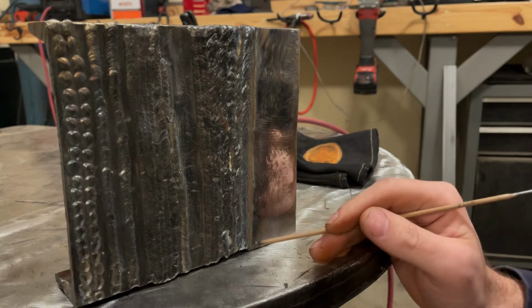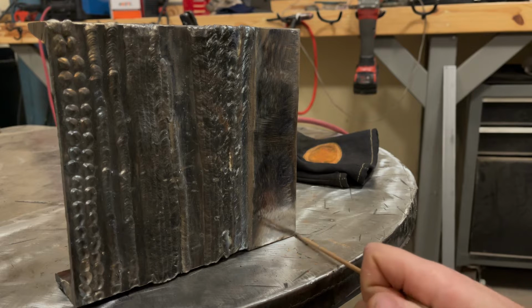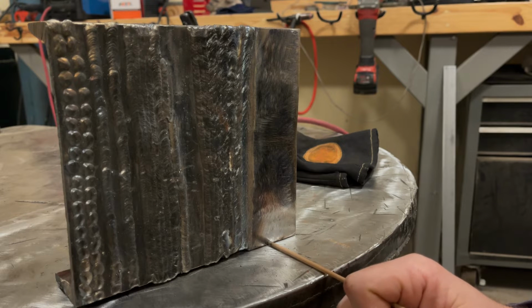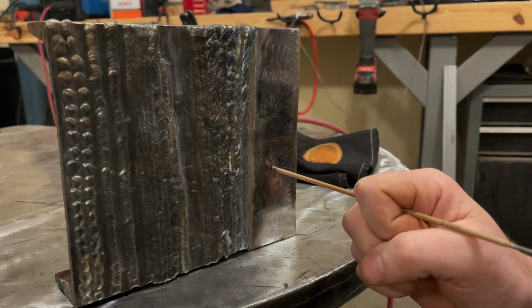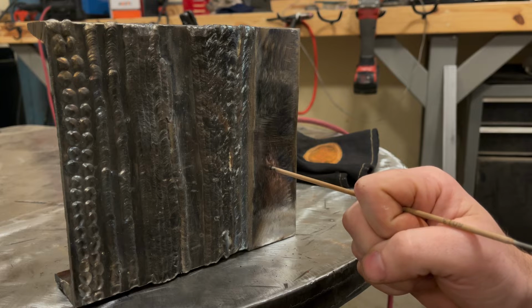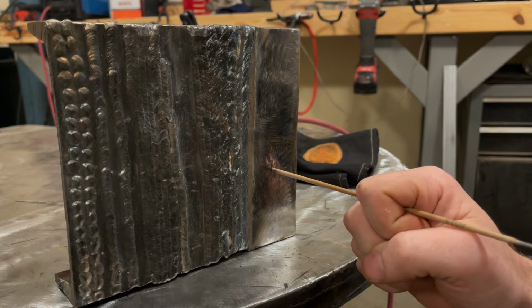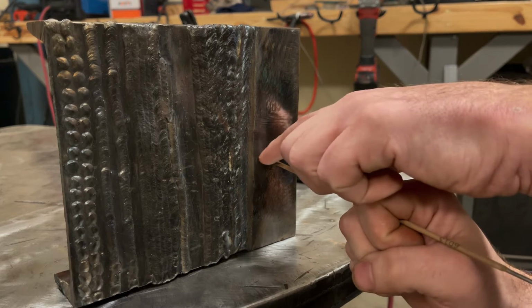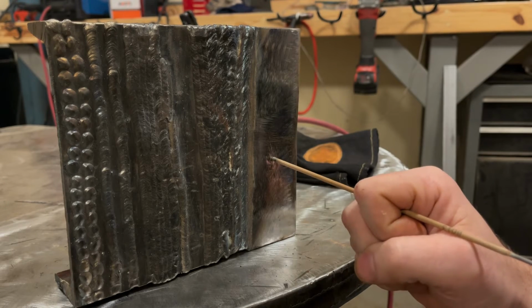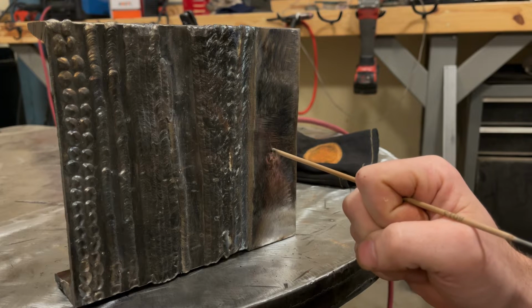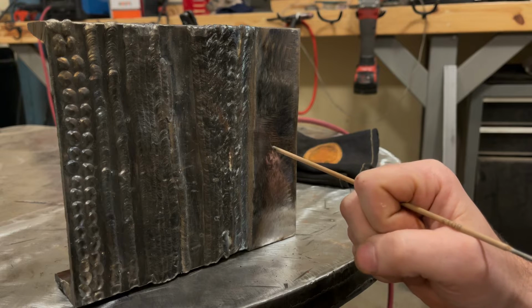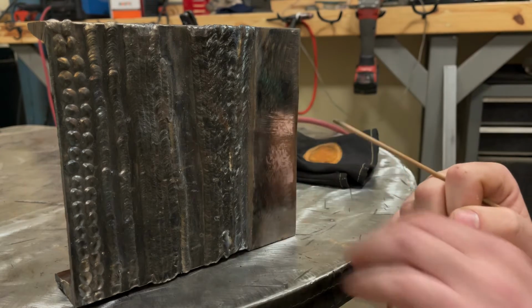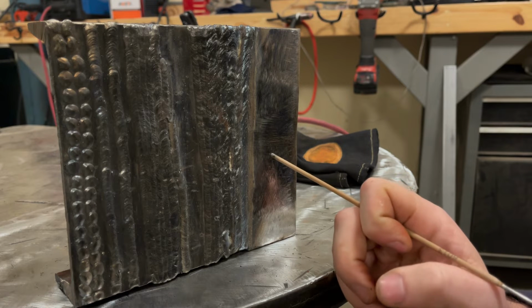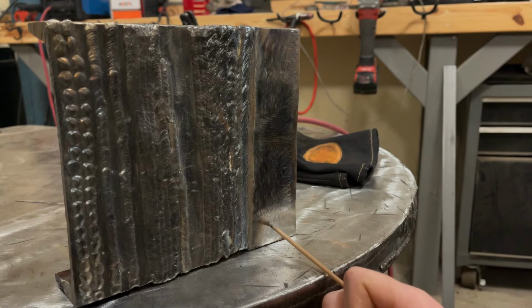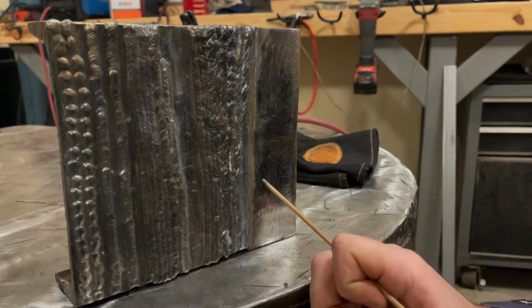So the first thing you want to do is take a rod, put it in your hand, and just practice the correct angle to weld uphill. Now, you can technically weld vertical up with a straight in angle. This is a straight in angle. It might not look like it because of the camera angle, but this is straight in. You're going to find with 6013 that if you have a straight in angle, the leading edge of your molten puddle is going to oftentimes undercut and underfill. And the longer you take to progress forward, the worse off your molten puddle is going to be because it's going to get so hot, it's going to drip or run or just get flat out too hot and out of control. So having a slight push angle like this is what you want.